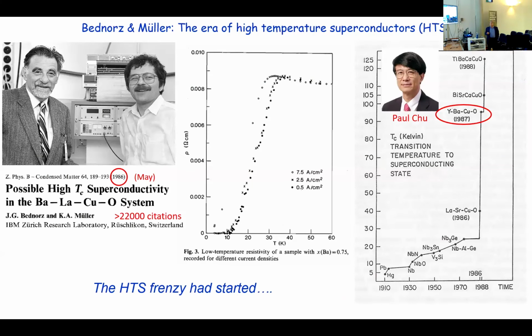And then the huge thing happened in 1986. Bednorz and Müller discovered superconductivity in the range of temperatures of 30 Kelvin in an oxide, in a barium lanthanum copper oxygen system, that was totally unexpected. This was very, very shaking of the scientific community, not only because the TC was higher, but also because it was going against the accepted knowledge that it was almost impossible to have TCs above 20-something Kelvin. So this was really revolutionary.